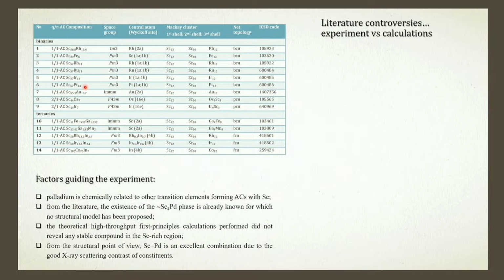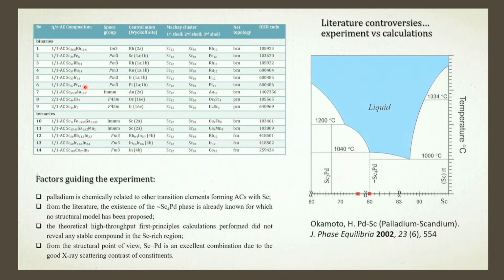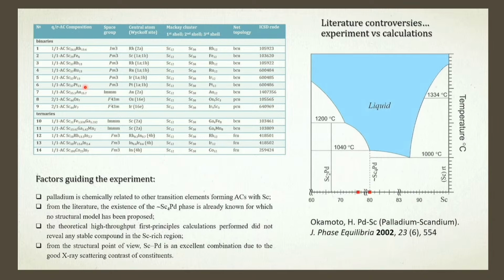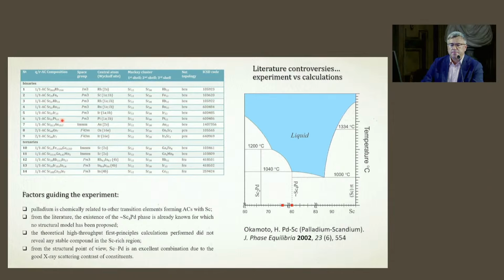The best choice was palladium for several reasons. Between scandium and palladium you have a good X-ray scattering contrast, so it's an excellent pair for structural investigation. Palladium is also similar to other components of this set. In the literature, data about the existence of this compound was already present, but no structural data had been published.